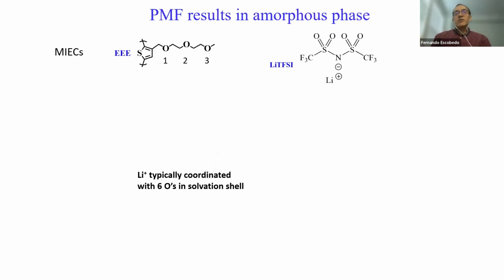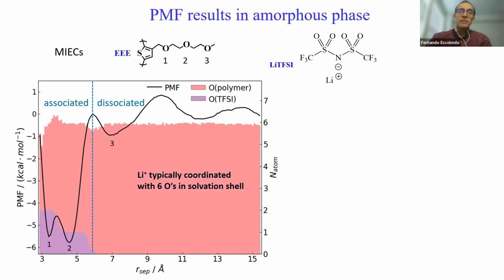So it's also important to understand the local structure of these materials. Again, this is the material we're simulating with this polymer, and it's the same salt as before, lithium TFSI. Typically, when the lithium salt is in this kind of environment, it is going to be coordinated with 6 oxygens, the oxygens that come from this side chain, in the solvation shell within a certain distance, the first solvation shell of the lithium ion. And if you look at the PMF, so basically what happens when you try to dissociate the 2 ions as a function of their distance.